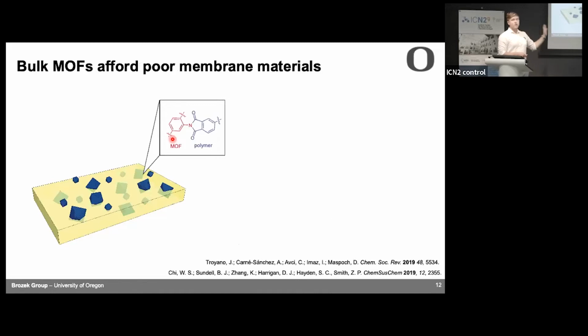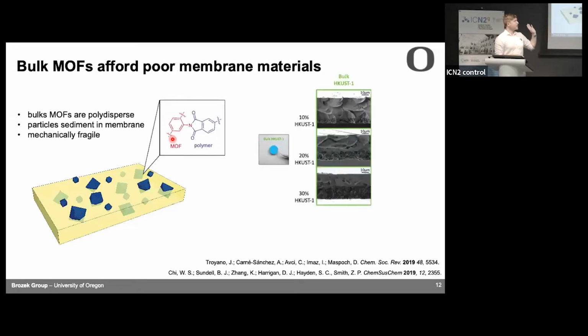However, when you work with these sorts of membranes and you're making MOFs from bulk synthetic methods, the membranes that you get can't really be used industrially. It's because industrially you want to be able to apply about 8 atmospheres of pressure against the membrane, and these sorts of membranes are not going to withstand that. The reason is that when you work with a bulk MOF powder, not nanoparticles, the particles will actually phase segregate from the polymer. So you don't really end up with a composite. You just end up with some polymer and some MOF, and then the thing falls apart pretty easily.